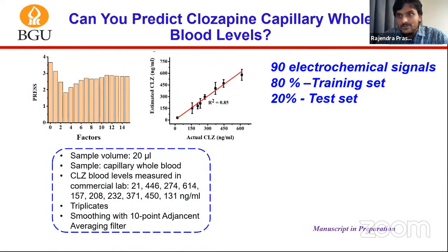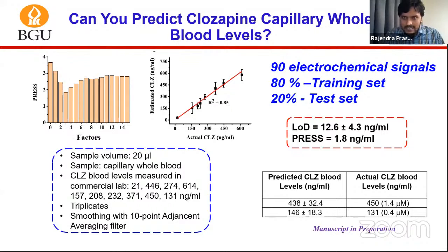So we were not limited to plasma samples only. We also did the same thing for whole blood, because we also try to avoid any pre-treatment step, since we do some centrifugation to obtain the plasma sample from the whole blood samples. So we followed the same approach as earlier. Here we got a limit of detection of 12.6, which is higher because of the complexity. We also tested the model performance for the prediction of again 450, and we got 438 with higher variance, and 146 for the 131, which is kind of overfitting.